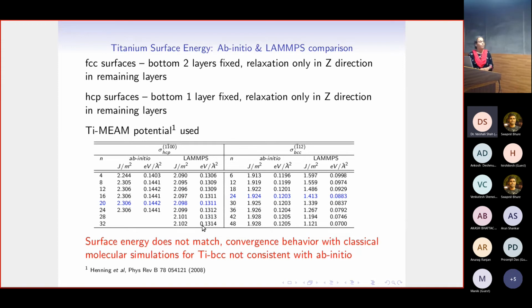Okay. But if we look at the energies that we get through the classical simulations, then one, the numbers don't agree. The surface energies that we are getting from the ab initio simulations are not the same as the surface energy that we are getting from the classical simulation. So that's the first problem we have, that the surface energies are not matching. And the second problem we have is that the convergence behavior that we see from classical simulation is very different than the convergence behavior that we see in the ab initio simulation.